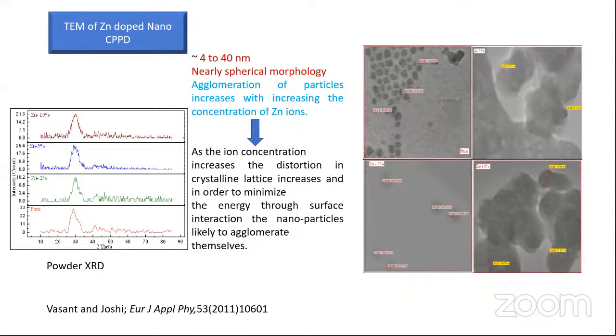These are the results of TEM and powder X-ray diffractogram of zinc doped nano CPPD, or calcium pyrophosphate dihydrate. The broad peaks show that amorphization is taking place. The average particle size is from 4 to 40 nanometers, and the particles are almost spherical in morphology. As the ion concentration increases, the distortion in the crystalline lattice increases, and in order to minimize the energy, surface interaction takes place and agglomeration of different particles occurs. These results were published in one of our research papers in 2011.